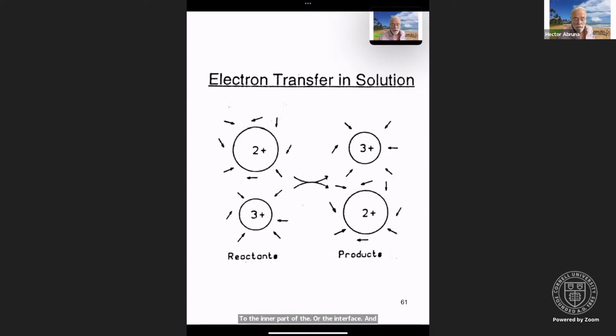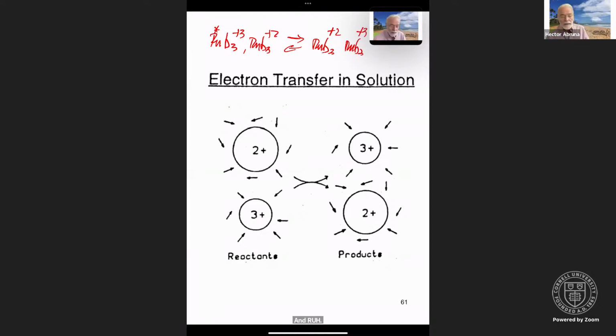And so if we go back to this idea of outer sphere electron transfer, if we think of a self-exchange rate, and here self-exchange means that the reactants and products are the same. So for example, if you take a look at, we go back to the ruthenium bipyridine 3 plus 3 plus 2, right? That's in equilibrium, let's say, Ru(bpy) 2 plus. Let's put a star here, meaning we can distinguish them, and Ru(bpy) 3 plus. This is a self-exchange process, meaning that reactants and products are the same.